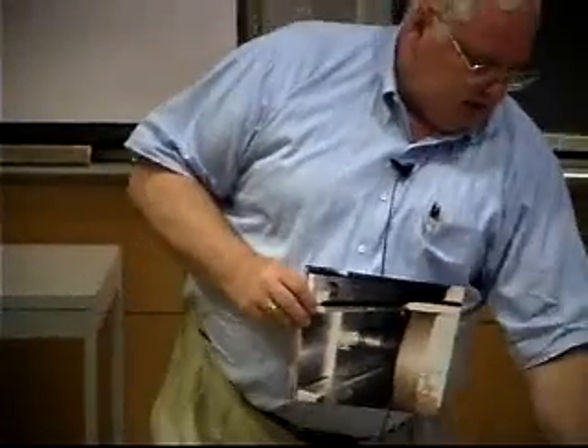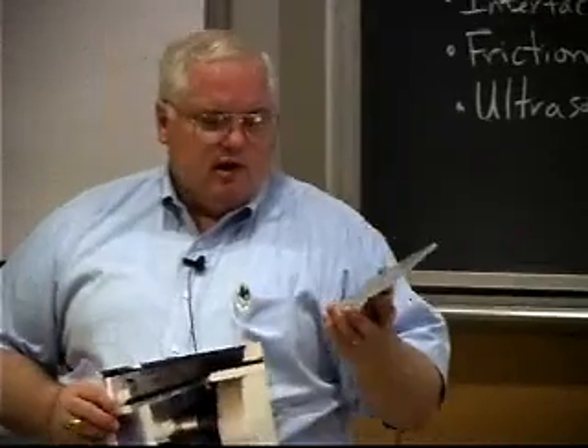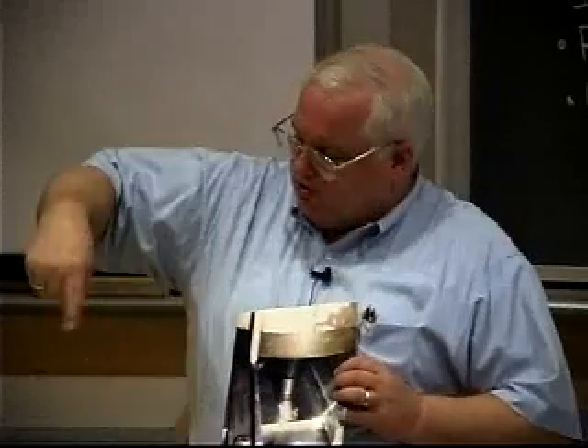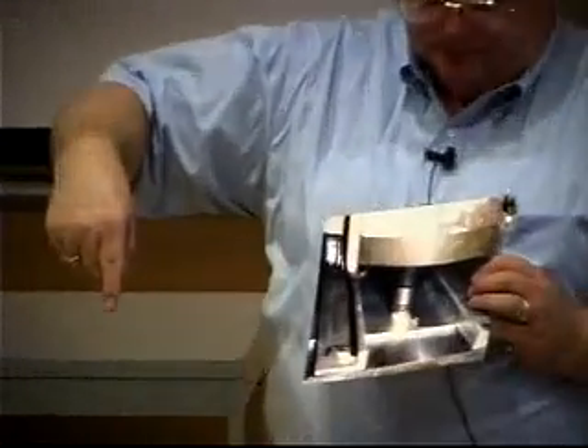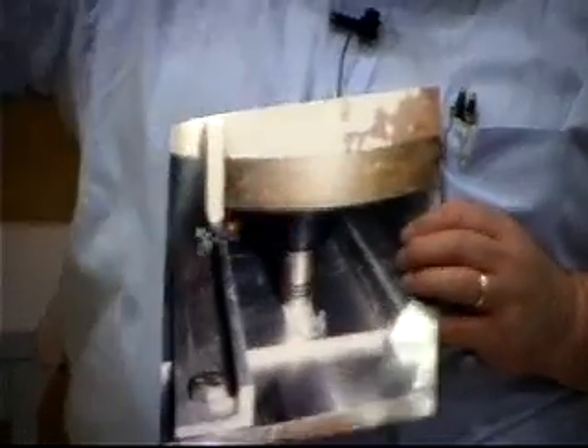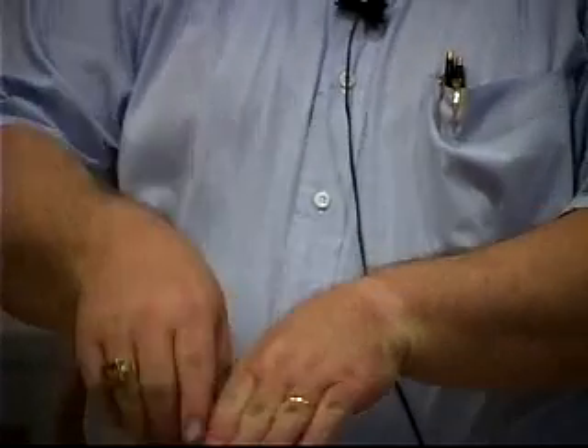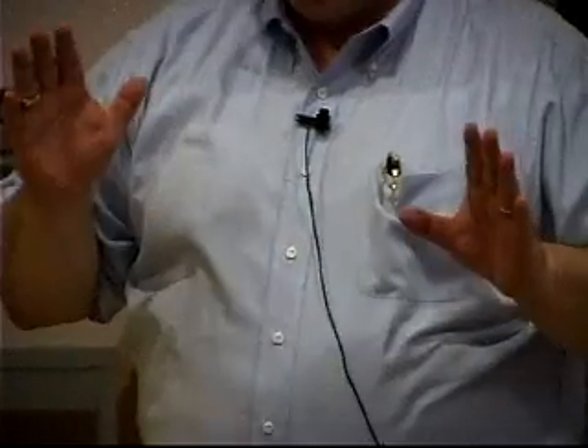I'll pass this around. Friction stir welding is a way to weld two plates together, typically aluminum, although there's a lot of research going on right now, and people are trying to weld steel and titanium and other things. But basically, you just have a rotating pin that goes between the two joints. So the pin is rotating this way between the joint, and it just stirs up the metal. You don't melt the metal, you just heat it, and you're basically forging it, and you pull this little spinning pin along. One student gave me these. That's a friction stir weld from NASA,